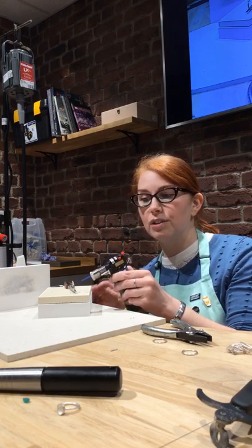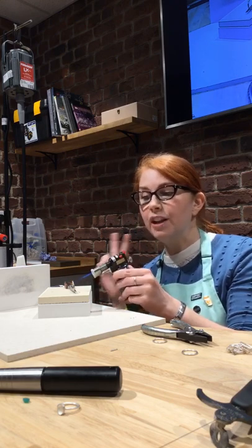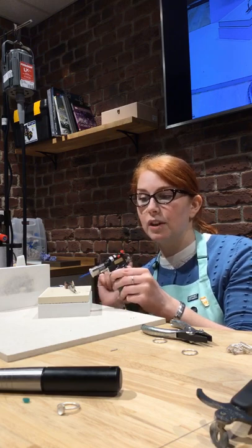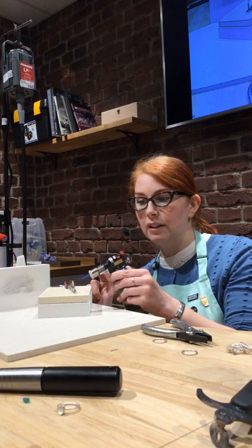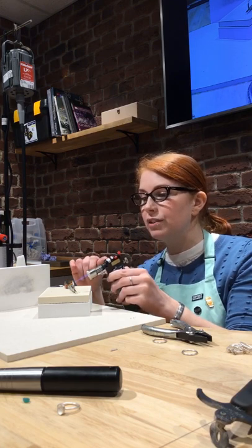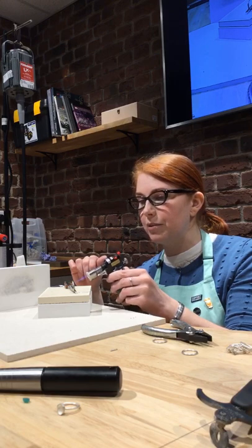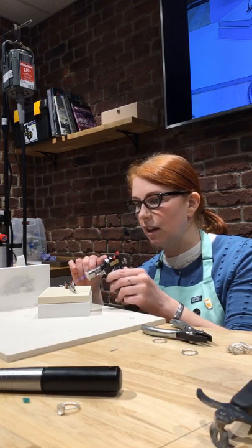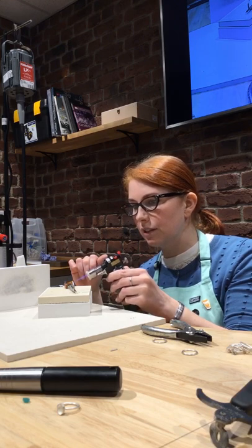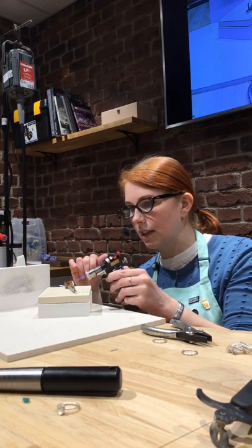If you're getting solder that's jumping to one side and not crossing, there's going to be two reasons. Either the gap is too big or one side of your ring is hotter than the other. Just started to ball up into a little ball. So we're almost there. The solder is at melting temperature, and now we're just going to get the ring up to soldering temperature too. So this torch is slower than my...